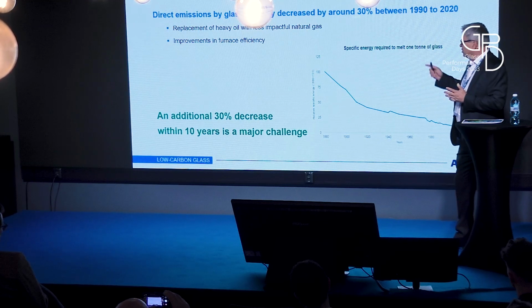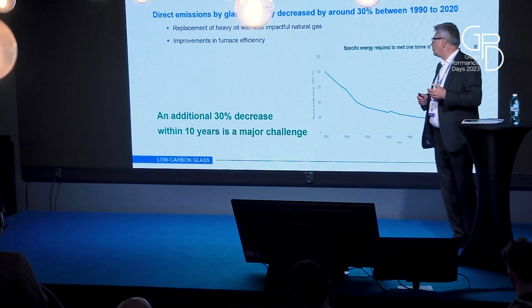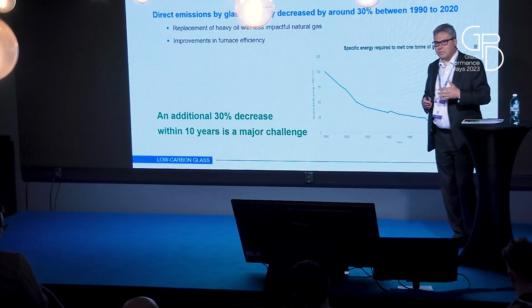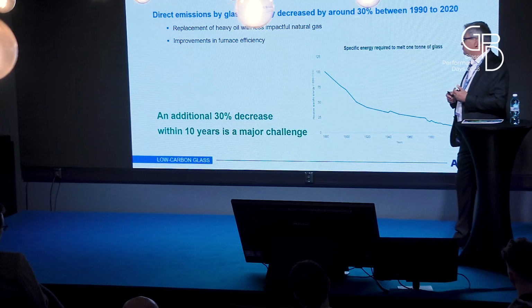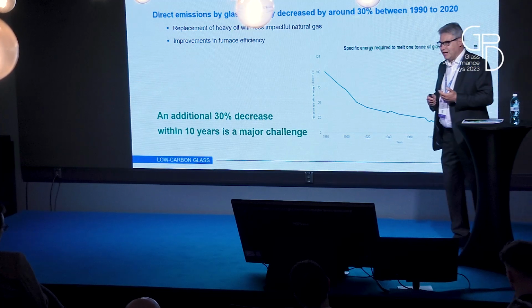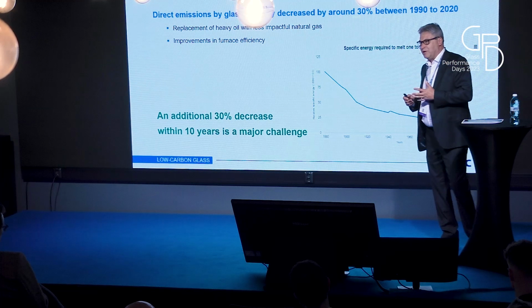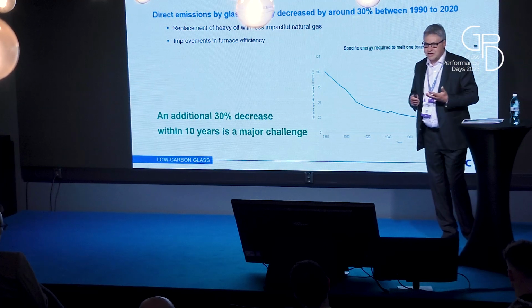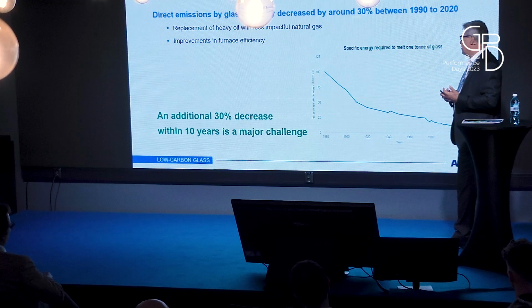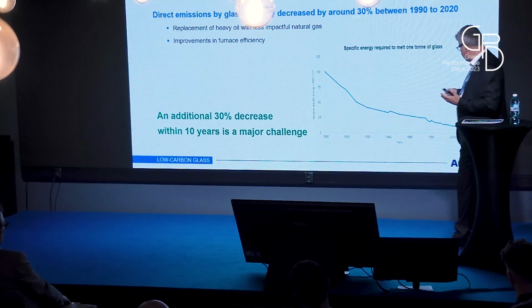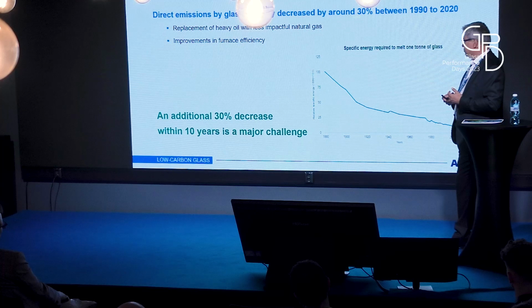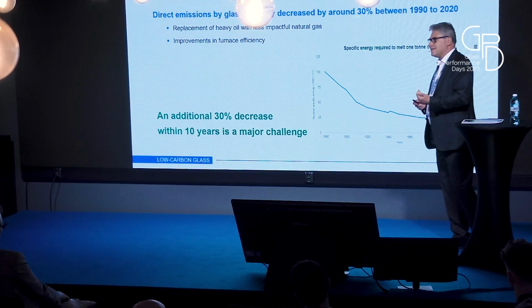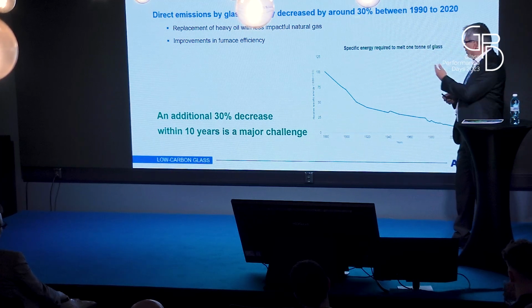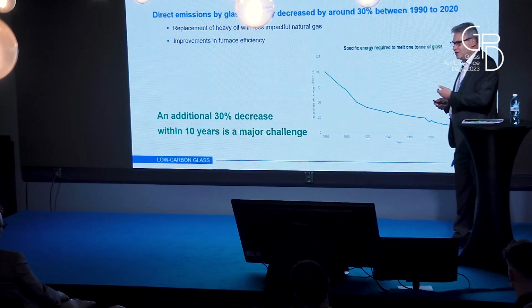It has been possible due to the replacement of heavy fuel by natural gas, and also the improved furnace efficiency. To be honest, it was more driven by economic reasons, to decrease the cost of melting glass. But anyway, it has been done, you see. So what we did in 30 years, decreasing by 30%, we have committed to do in less than 10 years. So it's really challenging because the easiest part has been done.